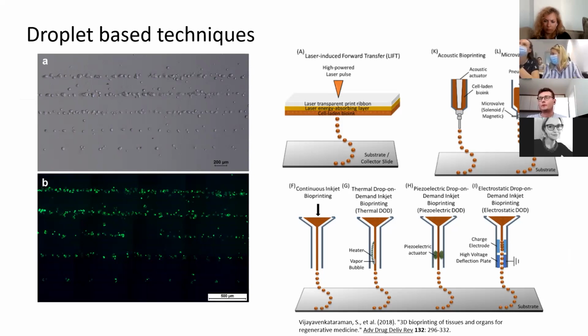Droplet-based techniques have been one of the first that were successfully used for printing living cells. Now they're becoming more sophisticated, but they're more limited in terms of the range of materials that you can use with them. You usually cannot use high viscosity materials because you have clogging or you don't get proper droplet deposition. But it has higher resolution, for example. So there's always a trade-off between the techniques you use, and you have to take that into account when planning certain experiments.